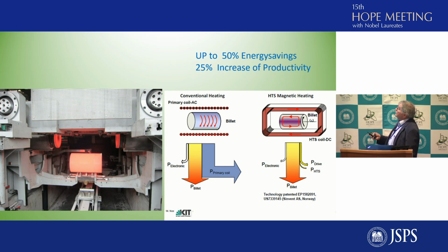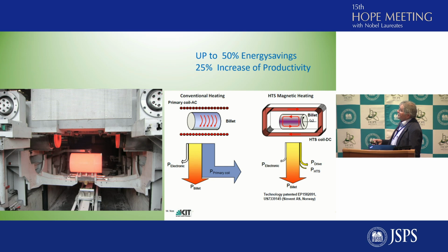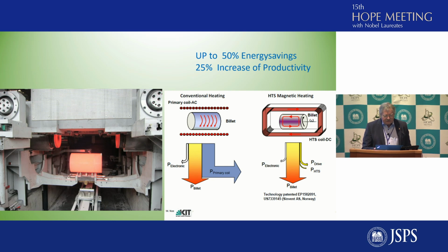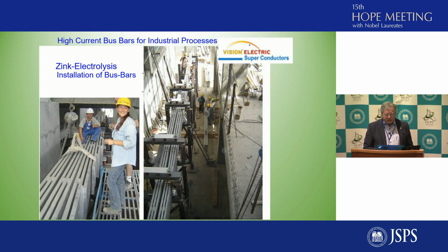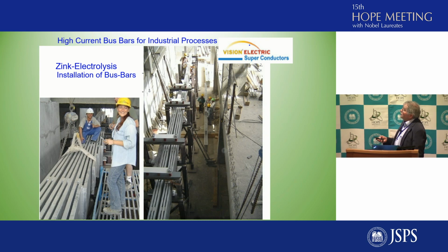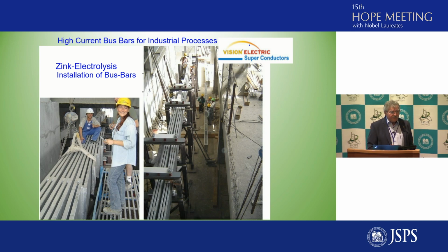This is a conventional heater, uses a lot of energy, goes from the primary coil. Only part of the energy is going to the billet. Here we see this billet being heated up to 600, 700 degrees centigrade, very, very rapid. And here is the magnet heater, which is saving up to 50% of energy. Another advantage is that the productivity is increased because the homogeneity of the heat distribution in the cylinder allows for higher pulling velocity.